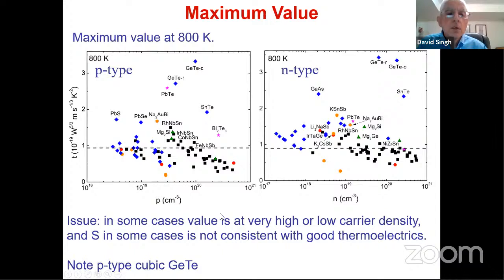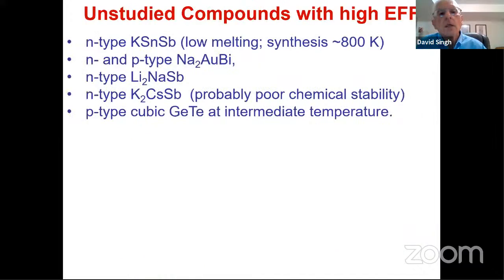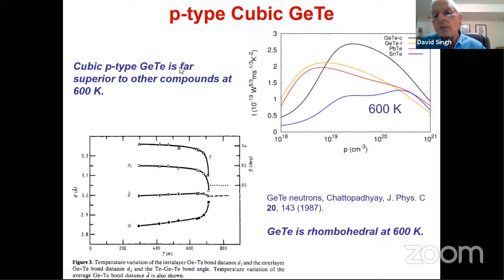Okay, so you can do that, and we find some interesting things. We find, for example, that cubic germanium telluride is fine. So we can find some compounds that way. And I just want to mention cubic germanium telluride. That was another material that experimentalists thought could not be made because at 600 Kelvin, where it's really good, it's not cubic. So what's the point of calculating a cubic material in the temperature where it's not cubic because it's rhombohedral there? But still, it's tempting because this fitness function is very high for cubic germanium telluride.